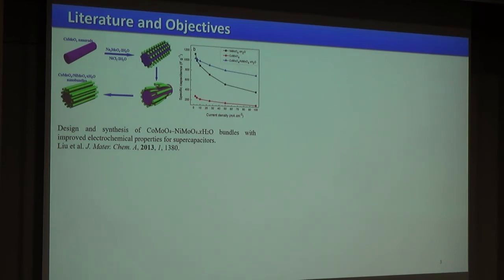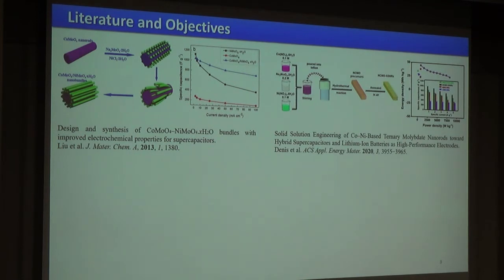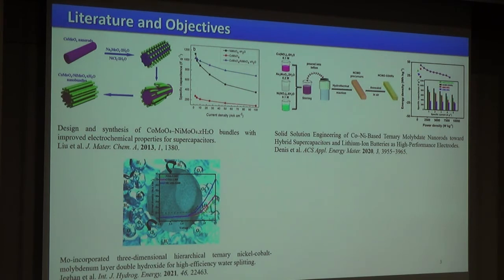In another work, this group prepared nickel cobalt molybdenate solid solution nanorods through a two-step process, that is hydrothermal and further post-thermal treatment. They also studied their energy storage activity in supercapacitors and in lithium-ion batteries. And in another recent work, nickel cobalt molybdenum layered double hydroxides were studied for efficient water splitting applications. So inspired by these earlier studies, we decided to investigate the energy storage and also the energy conversion applications of these nickel cobalt molybdenum ternary oxides.